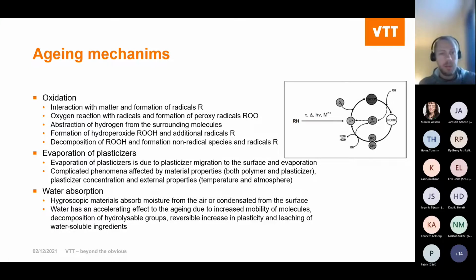So this oxidation process is self-sustaining. Then we have evaporation of plasticizers. Plasticizers are typically used in polymers to make them less stiff. So when these plasticizers are evaporated from the sealant, it turns rigid or stiff. The mechanism is related to plasticizer migration in the material to the surfaces, followed by the actual physical phenomenon of evaporation. This is a rather complicated phenomenon, and it's affected by several things. Firstly, material properties, both the polymer and plasticizer, and then of course plasticizer concentration, and then some external properties such as temperature and the surrounding atmosphere.